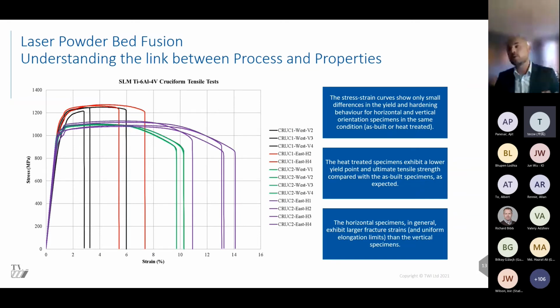Now, if you were to look at, say, an aerospace manual for Ti64 properties, it'd give you a yield around 1100 megapascals and a UTS around 1170. There's very little strain hardening. But the red and the black curves are in the as-built condition. They've got a much more elevated yield strength because of that martensitic, very hard phase. But their ductility is significantly less. And we also start to see some variation in ductility depending if it's vertically orientated, pulling layers apart, or horizontally orientated, pulling layers transverse to the prior beta grains.